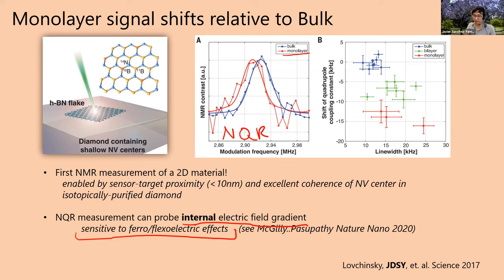But more generally, it was just a nice proof of principle that we were able to show that we can actually measure NMR signal from a 2D material. And this was enabled by getting both within 10 nanometers between the NV center and the material, and also the excellent coherence properties of NV centers in this isotopically purified diamond.